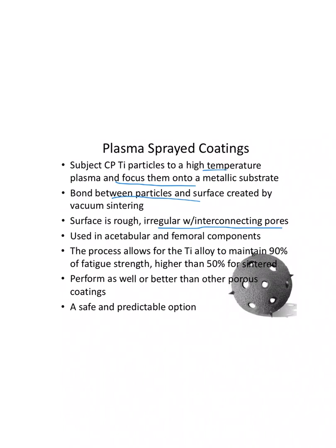And so what you do is you take that process and you make it even uglier by making pores predominant in that structure. It is useful because you make these components, you have a solid piece of titanium, and then you put porous titanium on top of it with this technology. All right, and so this has been used.